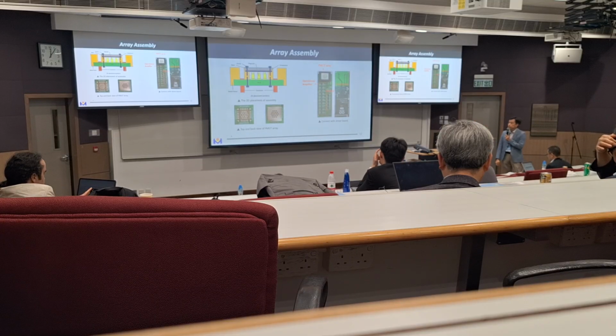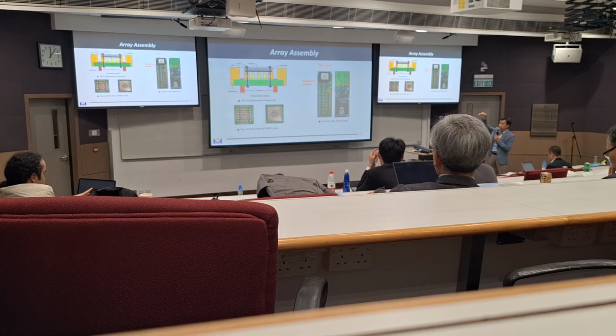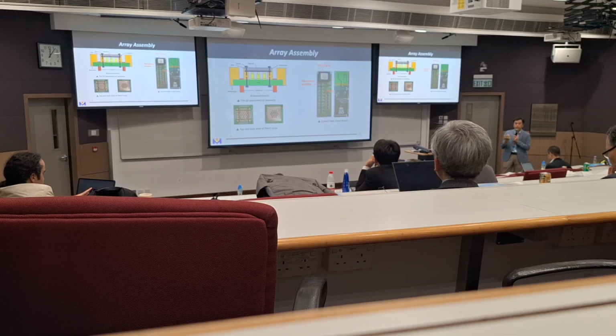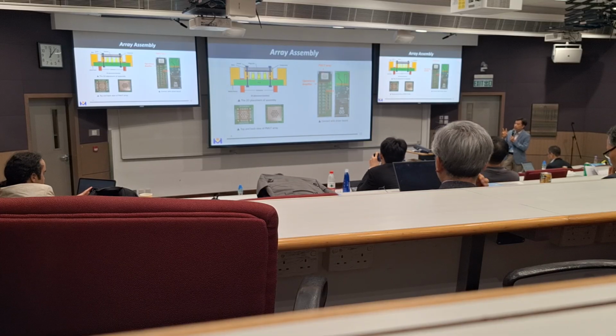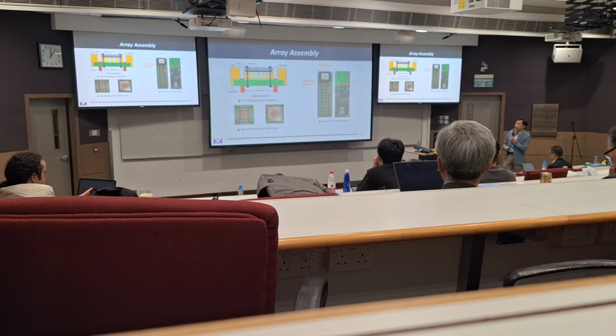Of course, for this kind of transducer, packaging design is also very important. We use a standard PCB process. On the top layer, the gray portion is our piezoelectric transducer, and then we have some pogo pins, which are spring-loaded pins, to touch the electrode on the bottom side of the piezoelectric layer. On the top, we of course grow some electrode, and then also on the top side, we glue the other stainless steel pieces to create an aperture, to design the aperture.